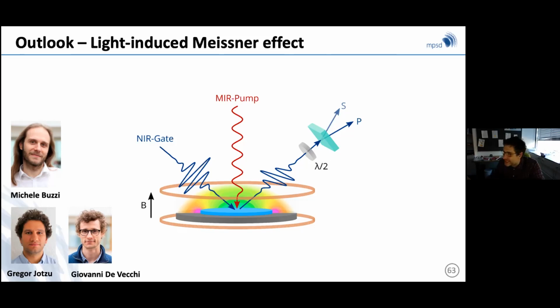superconducting or non-superconducting state, and then have a magnetic field that threads this sandwich of the superconductor and the garnet, and then use a time delay pulse to look at polarization rotation in the magneto-optical crystal, to have a quantitative local microscopic measurement of the magnetic fields. I expect to be invited again if this experiment works. We already have some very interesting results in which we can destroy a superconducting state and we can observe a field that used to be expelled not being expelled anymore.